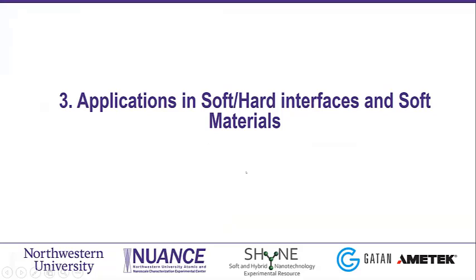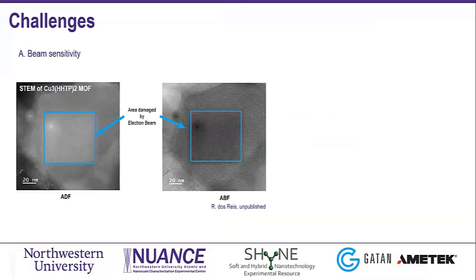So a few applications here that I want to show in soft-hard interfaces and soft materials using direct detectors. So one challenge of imaging this type of materials is, first of all, beam sensitivity, right? Especially using STEM with standard alignments or standard emissions, current emissions that you use for your hard material, right? So you basically destroy your sample after a first pass on your typical HAADF or annular bright field imaging here.